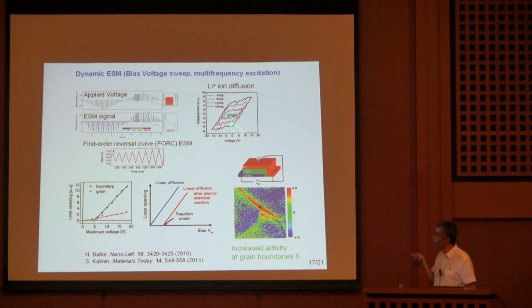You can perform a full spectroscopic analysis in each dot. So you can make an array of dots onto your surface, so you can explore the electrochemical activity over the surface of your material. So you can correlate this with any feature in your topography, like grain boundaries or some other defects. This is what is powerful of this technique. And this is room temperature analysis.